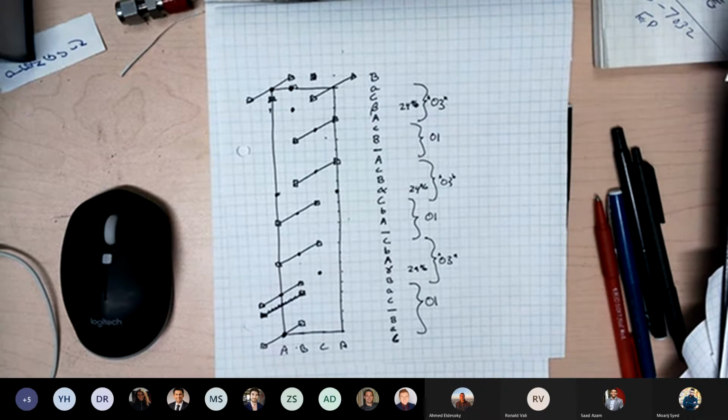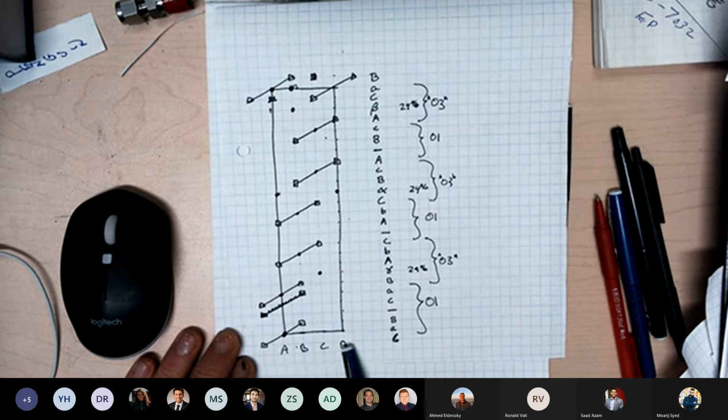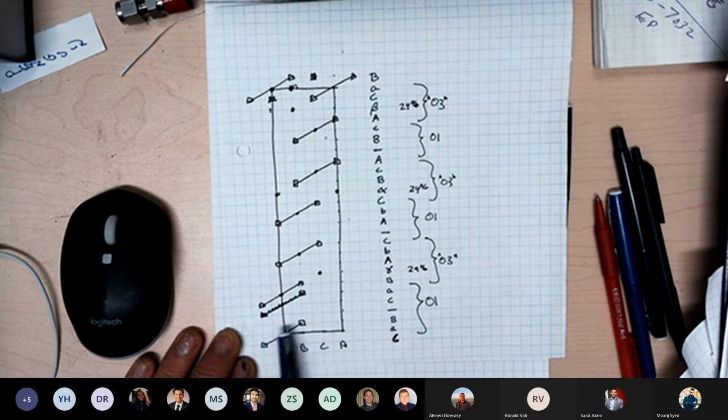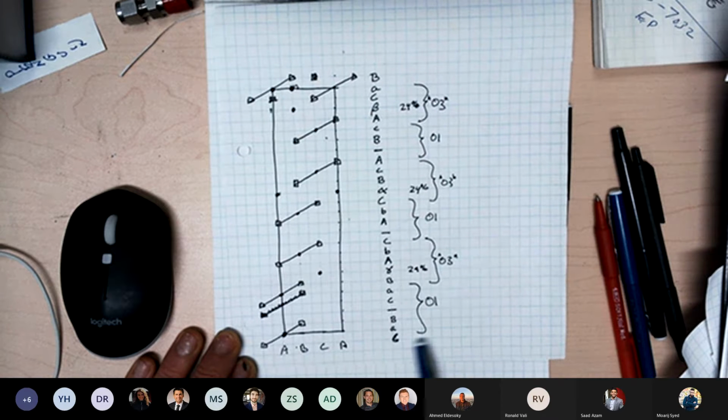So when you put the stacking sequence down, A, B, C, A, you start with oxygen, you have transition metal on A, transition metal and oxygen on B, and so on. This first pair of cobalt oxygen slabs at the bottom has no lithium in between at all, and they are stacked with cobalts one on top of each other. This is what you find in O1, cobalt dioxide, or in titanium sulfide. When there's no lithium between the layers, it likes to be in this O1 sequence.